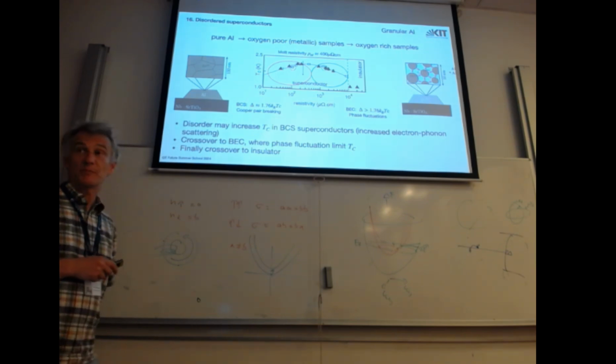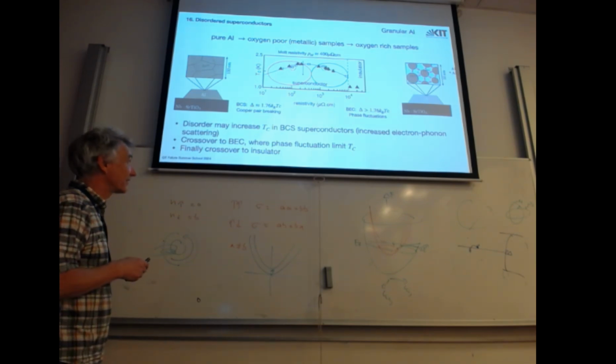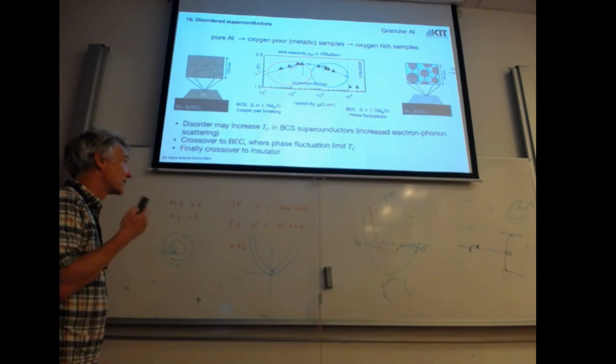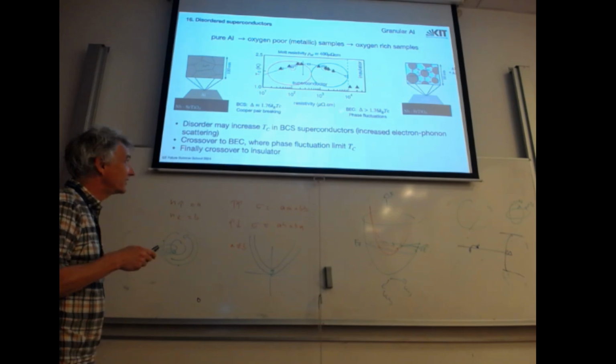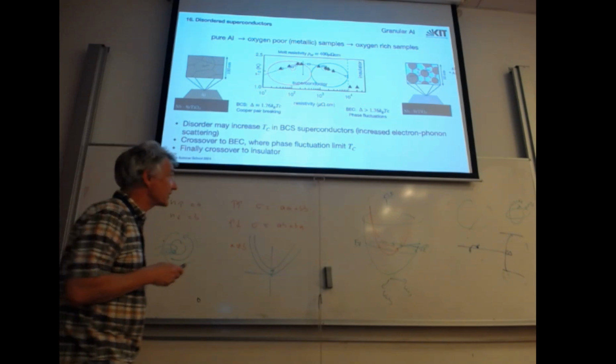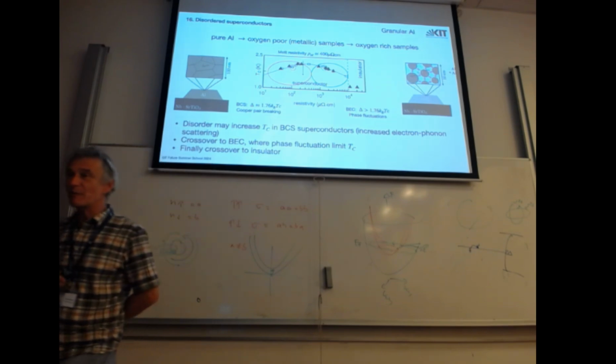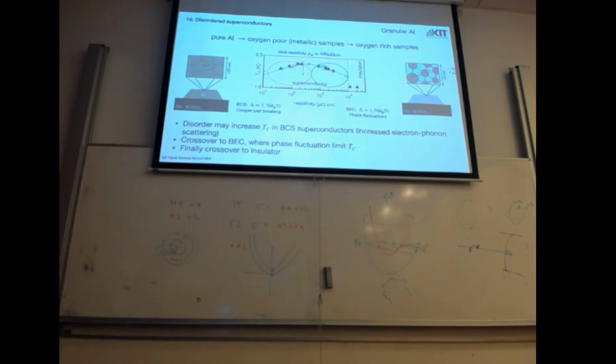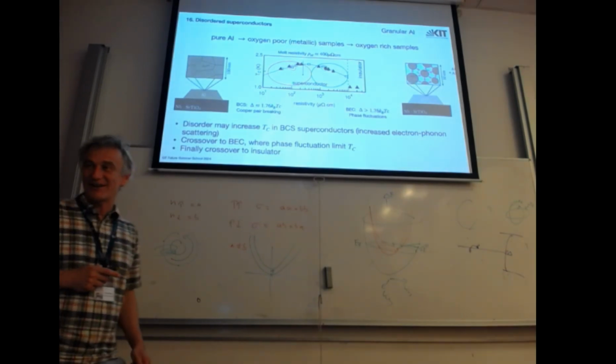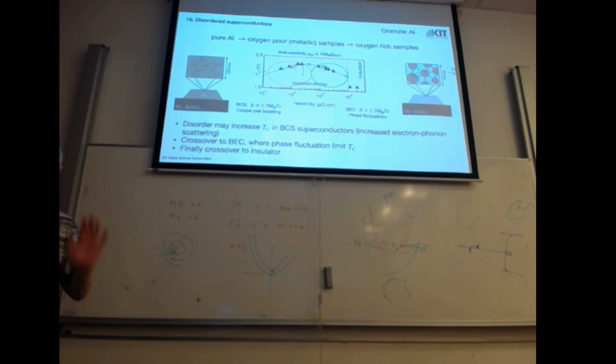So it's not a BCS type superconductor, and some authors claim that here the transition to the normal state is not happening by breaking up of the Cooper pairs like in BCS, but by Bose-Einstein condensation. So you always have Cooper pairs, but they become coherent at a lower temperature. That was also the paper that we discussed in the first lecture, which is still under dispute. So this is under dispute.